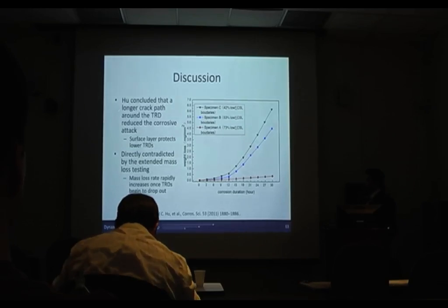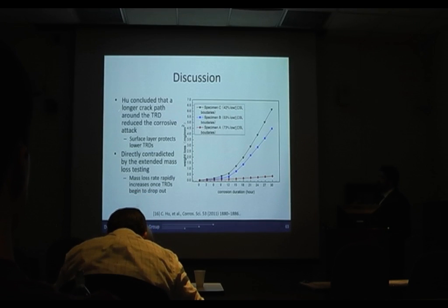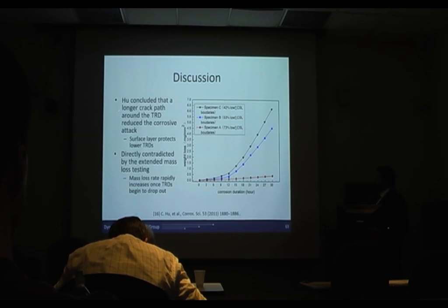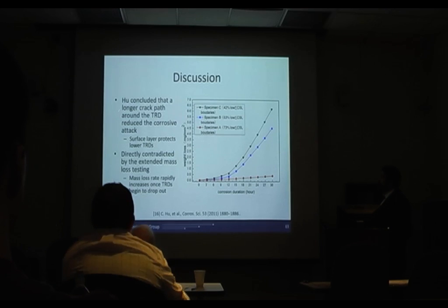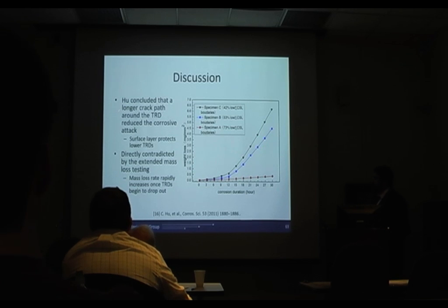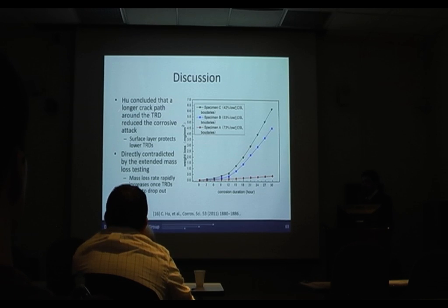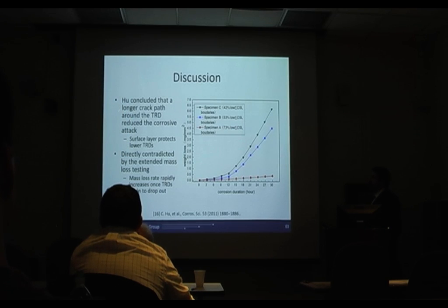And when he plotted the mass loss, he was actually looking at three different conditions with different levels of CSLs. And the two lower conditions, you can see this rapid increase in the mass loss rate around 12 hours. However, specimen A with 73% CSLs sees a much, much lower increase in the mass loss rate. And he attributed this to the TRDs. Total mass loss is not rate. Sorry, yes. He was reporting total mass loss.